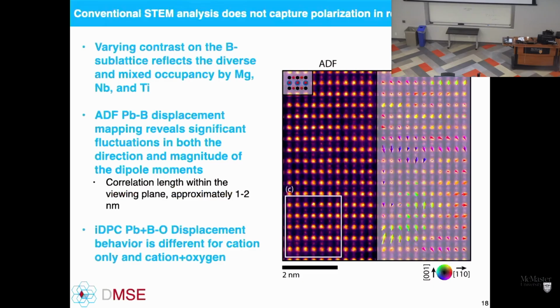So in conventional STEM analysis, we can try and apply this to these materials, and that's what we had done previously. And what we can do is use this to identify where our magnesium, niobium, and titanium columns are, and map out their displacements relative to lead. These would be what were often used as a proxy for understanding polarization in the microscopy community, but it didn't include oxygen. So you got displacements of your cations, but if you only have cations, a dipole that does not make, right? You have to have oxygen.